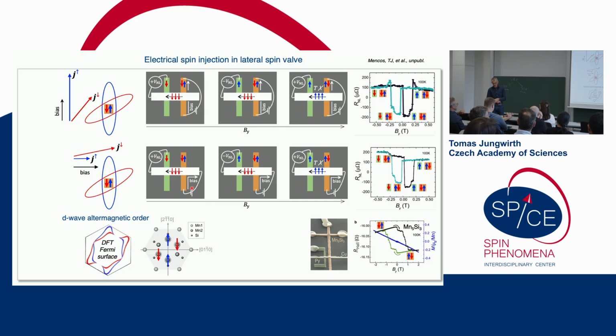Of course, without altermagnetism, you wouldn't have anything. But in an altermagnetic phase, you could have a situation where the interface lowers the symmetry in such a way that your two sublattices are present unequally at the surface. So your surface would be polarized because of that, and not because of the reciprocal space. Yeah, it could be, but the altermagnetic phase, without any of these additional effects, can explain it not only qualitatively but also semi-quantitatively. So that's the only answer I can give you. But I can definitely not exclude it.